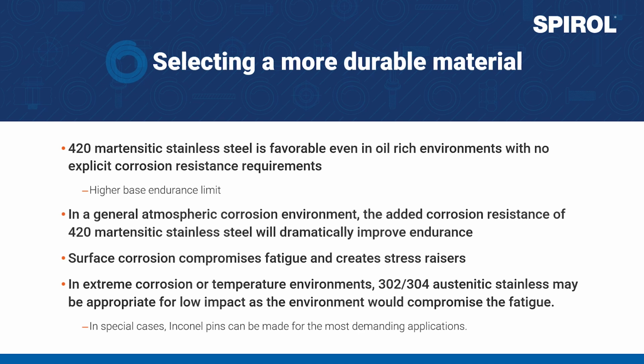And the increase in service life by switching to 420 martensitic will be dramatic. Martensitic stainless steel is not the solution for all applications, though. In extremely corrosive or high temperature environments, the better corrosion and temperature resistance of austenitic stainless steel would actually make it function slightly better. And in the most special of cases, we can also look into using 316 stainless steel for its even superior corrosion resistance, or even Inconel for some of the ultra high temperatures or sour gas environments.